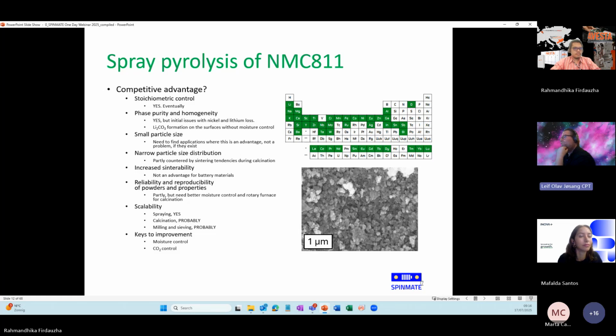Small particle size, well, that's not necessarily a huge advantage for battery cathode use. So if we're going to have commercial success with NMC through our production method, we need to find narrow applications where smaller particles is an advantage and not a problem. The narrow particle size we have is partly countered by sintering tendency during our calcination step for NMC. There's a minor liquid phase that forms that we'll see in some pictures later.